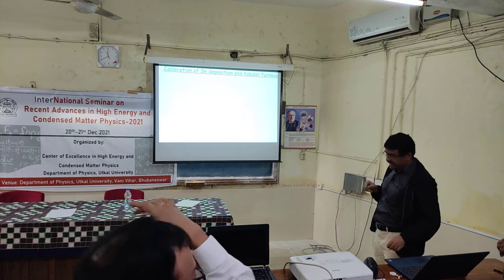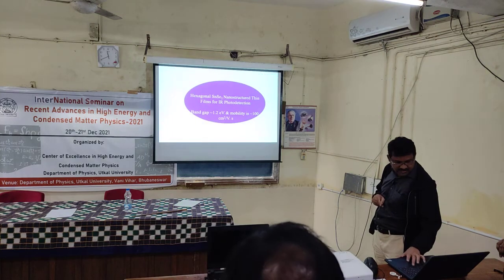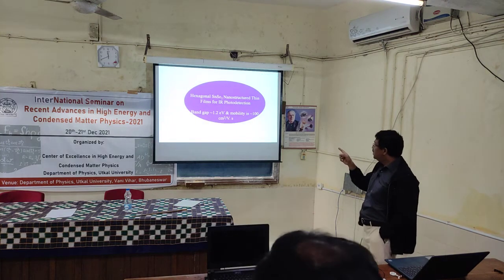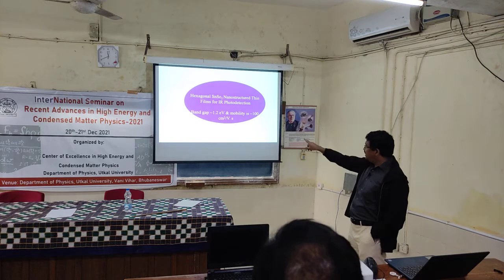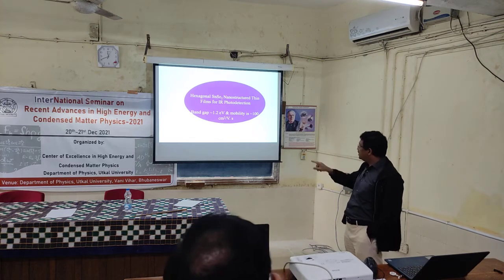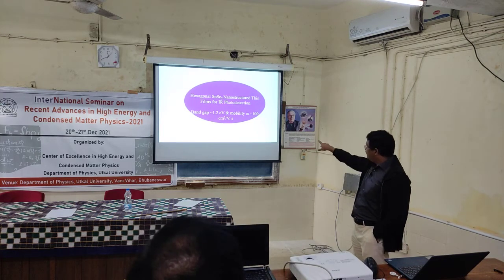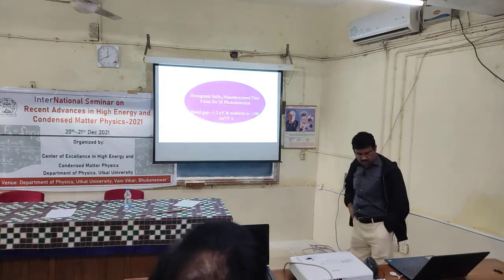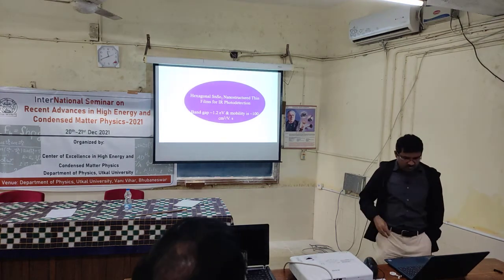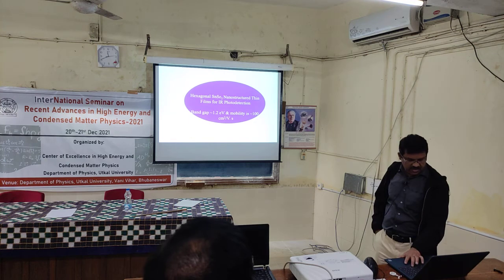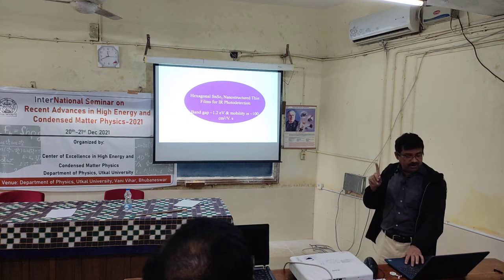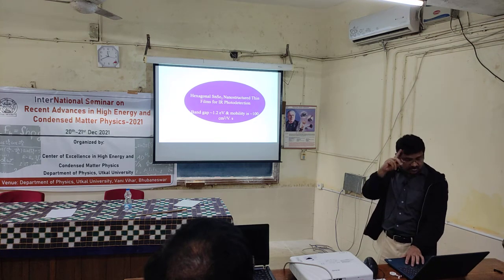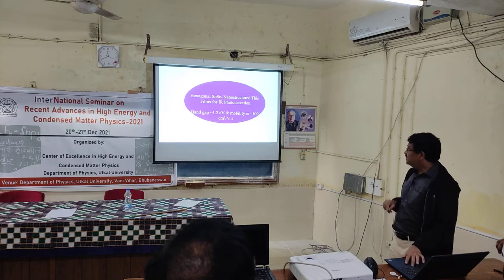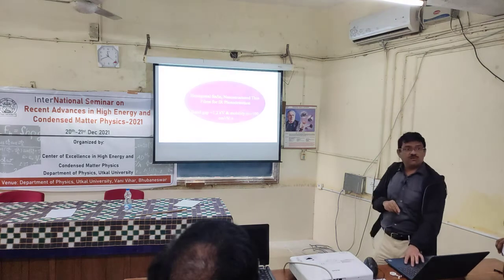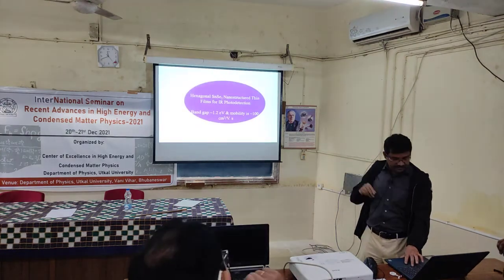So before that, we have dealt with a SnSe2 nanostructure thin film for IR photon detection, because the band gap of this SnSe2 system is 1.2 electron volt, and the mobility is 100 centimeter square per volt per second. The band gap is good, but the mobility is not that great compared to other semiconductor systems. But then we thought, let's explore this, how it is going to behave.